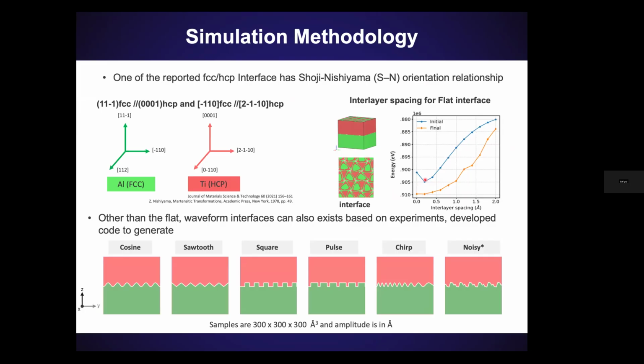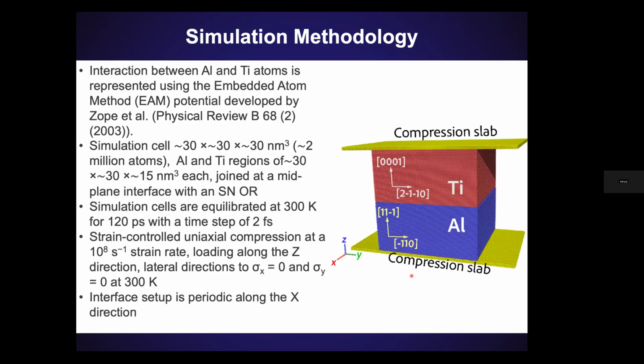But like I told you, I was interested in how that interface morphology or the shape affects the dynamic behavior? And MD lets me do that. So we wrote a special code that lets us essentially change the interface shape in different ways. One thing we did is we formed a wavy interface. This was important because some of our experimental detective work had shown us that a lot of these interfaces tend to be wavy at the atomic level. We also wanted to see, well, what if I don't have these rounded kind of cosine waves and I had a sawtooth interface? Does that help me improve the dynamic behavior of the material at all? Well, what about this square shape? Maybe that would be better. Wider squares or any kind of, you can pick and choose. I won't go into all the details because I have a ton of slides to show you.